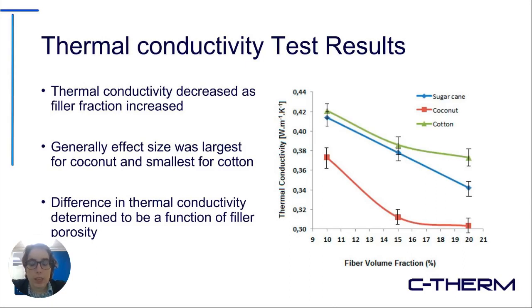As would often be expected, these kinds of organic filler materials tend to be fairly porous. You would expect, and indeed the researchers did observe, that the thermal conductivity decreased as a function of the filler volume fraction. It also appeared to relate to the filler porosity level, which is, again, what would typically be expected of this sort of relationship.